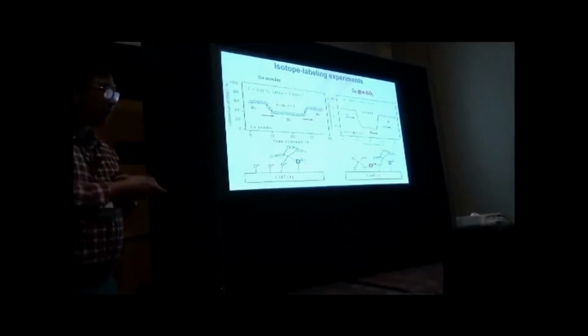And also, in this case, we can use sodium hydroxide to remove the hydroxyl groups here. In this case, the KIE of the silica copper system will come back to that of the copper system. When the interface has been blocked, it comes back to the copper system. So it can confirm our mechanism.